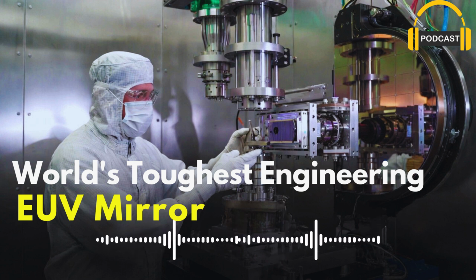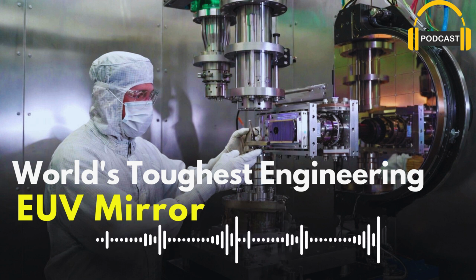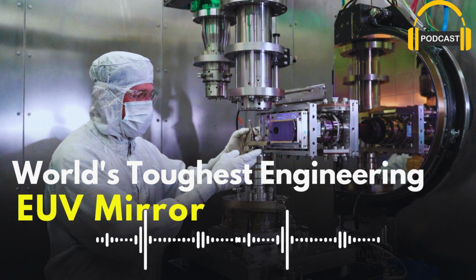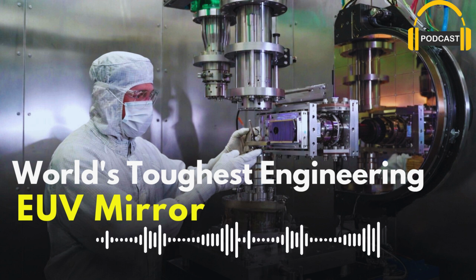A few years later, in 1978, Spiller met Troy Barbee at Lawrence Livermore National Lab. Barbee had invented a new way to deposit those thin layers called magnetron sputtering. It's like sandblasting atoms in a vacuum chamber so they land perfectly flat on the surface. With this technique, they could control thickness down to fractions of a nanometer. Suddenly, reflectivity jumped. They hit over 60% reflection in some tests. That was huge. For the first time, people started believing EUV mirrors weren't just theory.